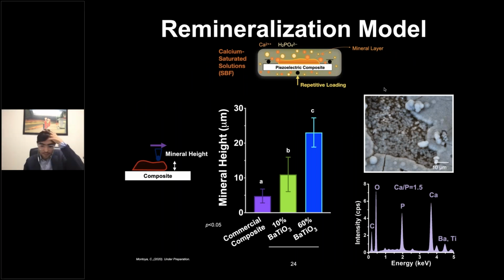So we do a 7-day experiment in which we put the sample under cyclic loading for 7 days, and after the 7 days, we assess how much mineral is formed on that surface.